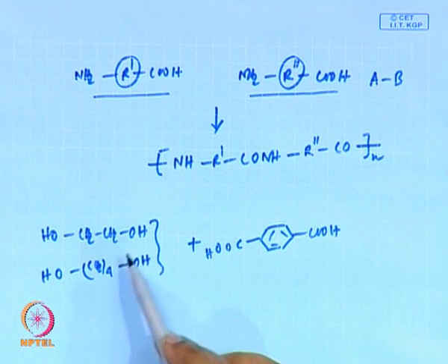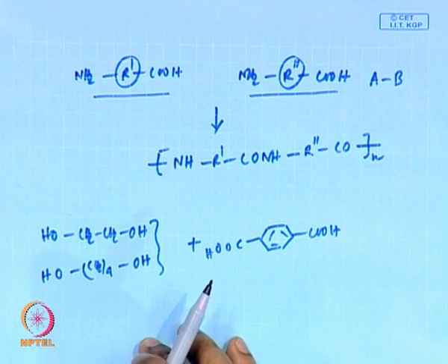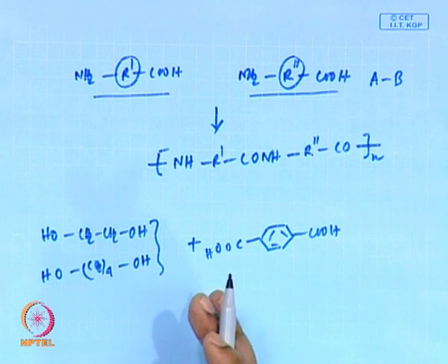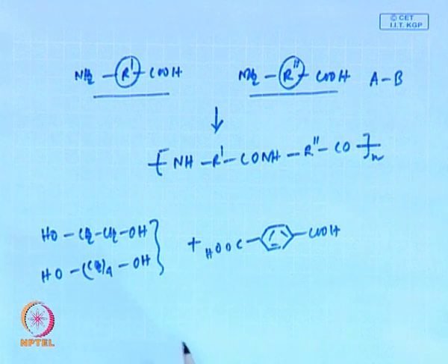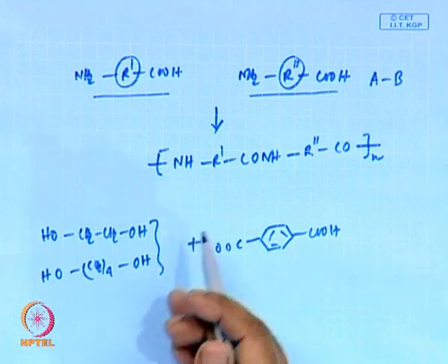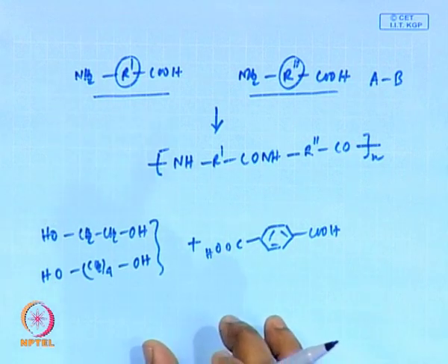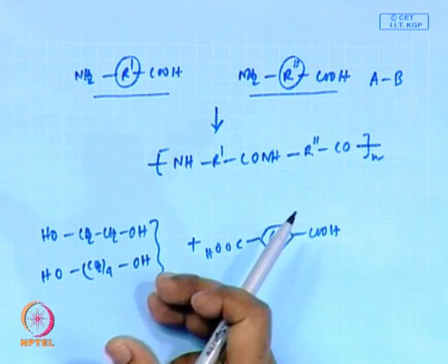In the normal step polymerization reaction, because this goes through a thermodynamically controlled process, the byproducts also take part in the reverse reaction and the intermediate chains also take part in exchange reactions between them. So, they are always reshuffling during the entire reaction.